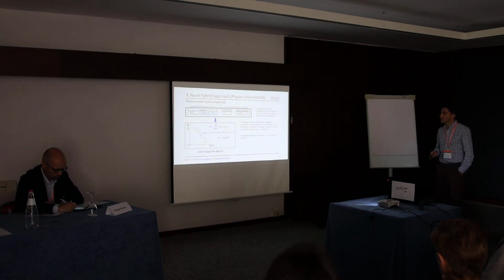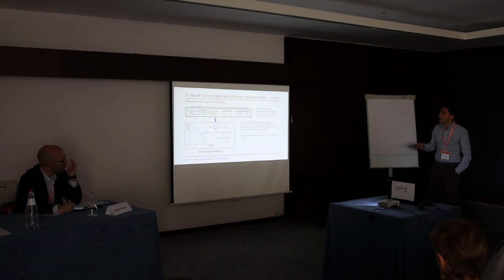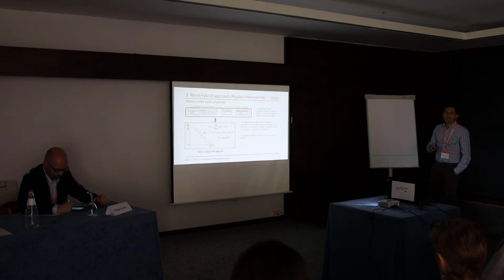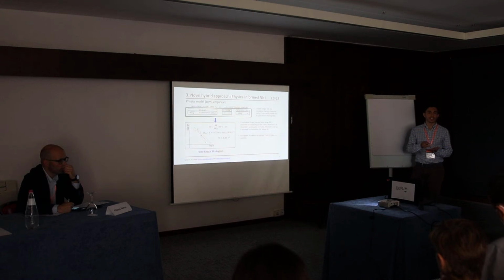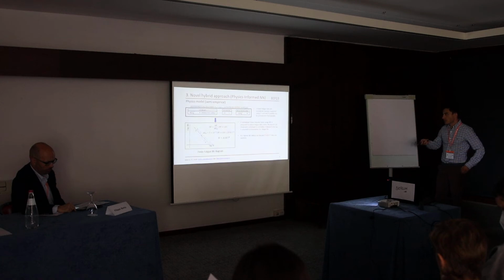And then from that, we can put everything into something analogous to an S-N curve. This is the stress intensity factor range versus the logarithmic number of cycles. But we decided to normalize the stress intensity factor by the stress intensity factor threshold, because we know that for short cracks, as Murakami has shown, the stress intensity factor threshold changes if the defect size changes. So we're going to show you later that this is quite effective. Then we fit everything with a Basquin-like curve, so it's a power law.